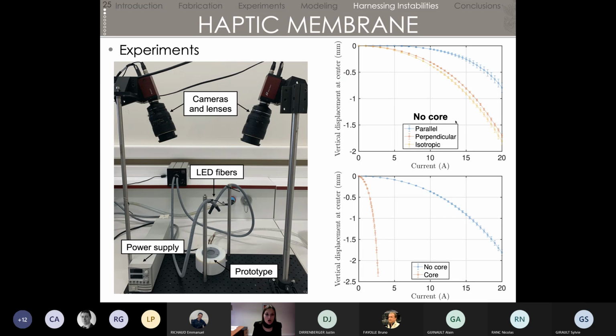So what we did also with this setup is do digital image correlation, stereo correlation here, to be able to measure the deflection of the MRE layer depending on different conditions. So the first thing that we did was use our 3 types of structuration of particles, namely having the particles parallel to the field, perpendicular to the field, or simply isotropic. It turns out that here any structuration actually stiffens your material. So in the end, the material that works better for this kind of applications are the isotropic materials, which is even better for us because they are easier and faster to make.